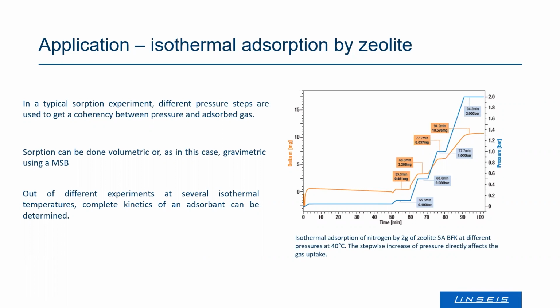And typically what's done in the absorption setup, the magnetic suspension balance is used to monitor the weight. And then you increase the pressure from low pressure to high pressure. So on this graph, you see a blue curve, which is the pressure that was increased stepwise from vacuum level to ambient or double ambient pressure, so 2 bars. And by increasing the pressure stepwise, you can see a response on the delta M signal, so the mass increases a bit. There is a little drift at the very beginning, which sometimes happens if you operate in vacuum. However, it's still a considerably small drift over time. And then you can see the mass increase steps quite properly.